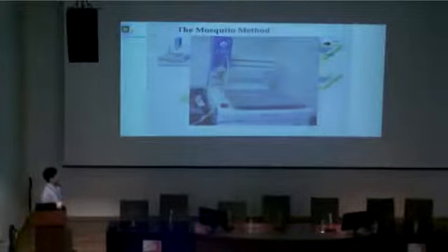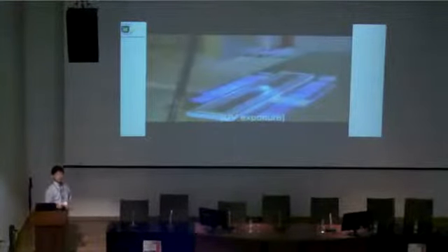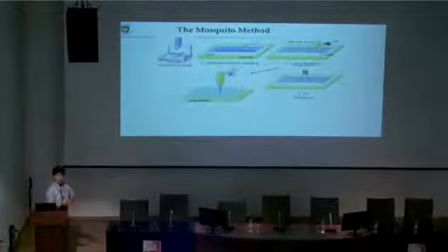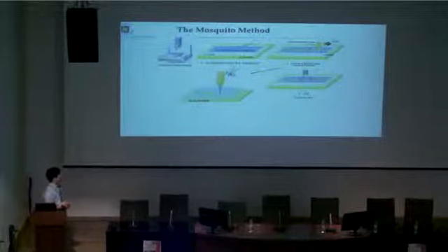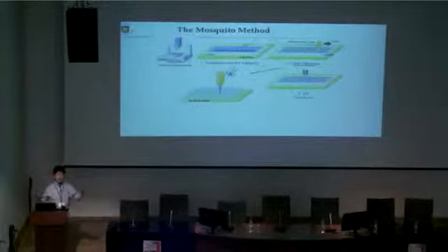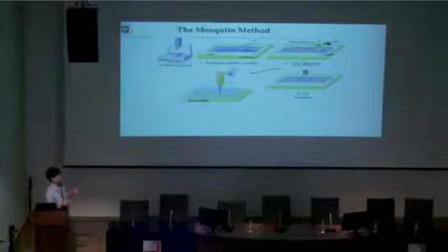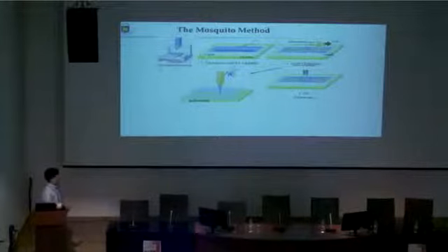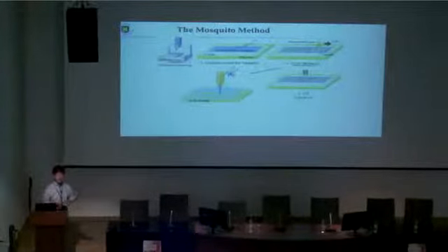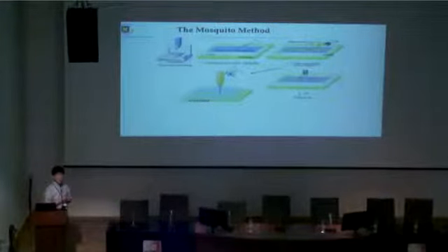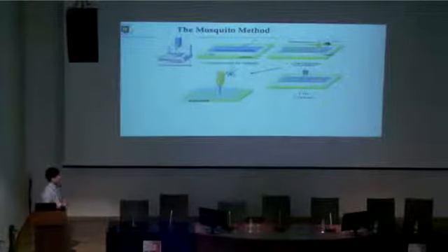So we are using this desktop robot, and this is a syringe, and you can see the movie like this way here, core dispensing. This is actual speed for one core, the neighbor cores, and then we can use just a UV LED for curing. So we no longer need any UV exposure machines. And then the waveguide size is not limited by a UV exposure machine, but just the stage size of this robot. So if we can obtain a large stage for the robot, we can make 1 meter or longer waveguides.